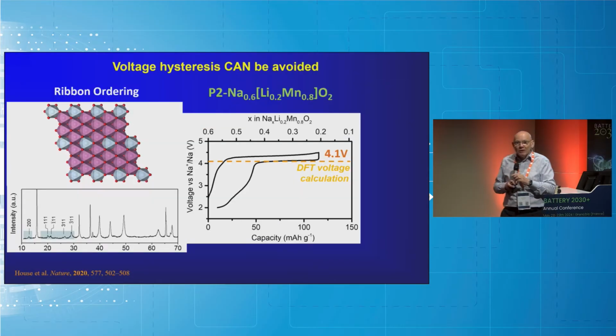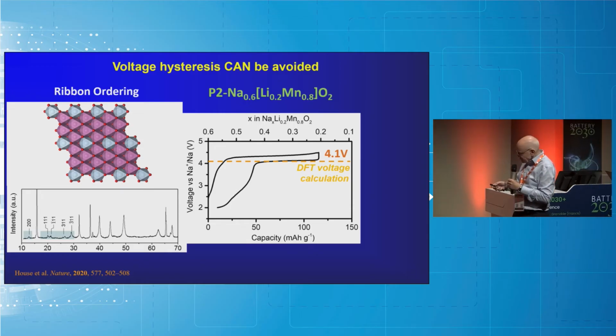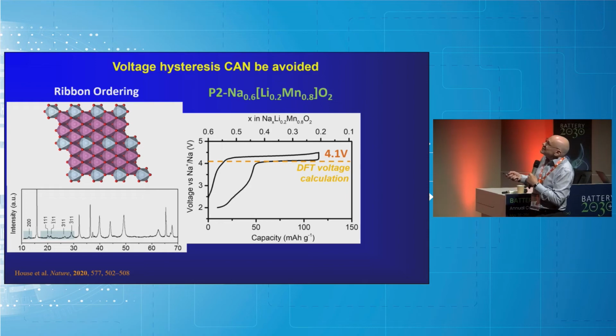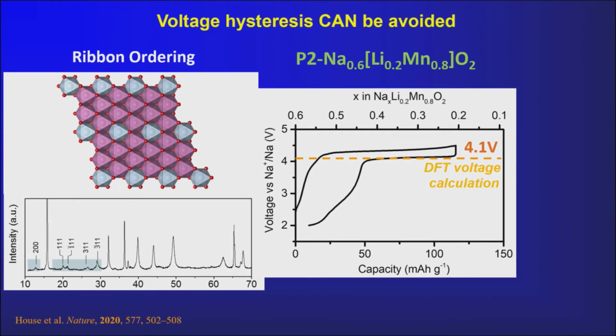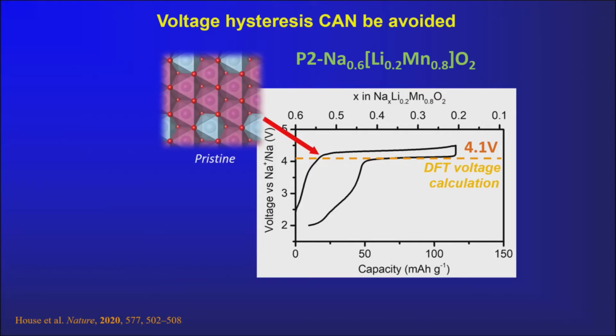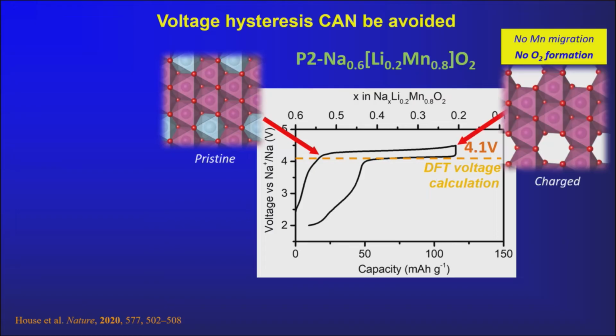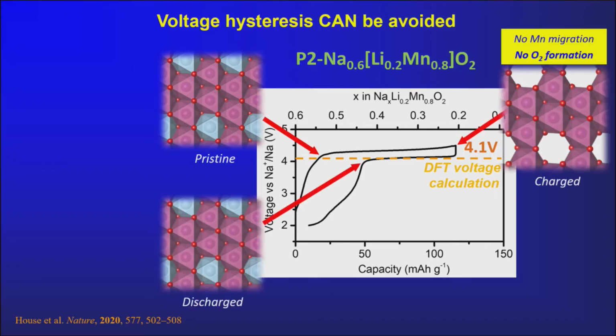So none of this we really want. We don't really want O2, and you don't have to have it. Here's a different arrangement, not honeycomb, from this compound here. Sodium again, but with lithium in the transition metal layers. And it's a ribbon structure, so not a honeycomb. And here's a reversible plateau. This is what we want. So in this case, we take lithium ions out of the transition metal layers, like this, and we put them back in the same place, so it's energetically reversible.